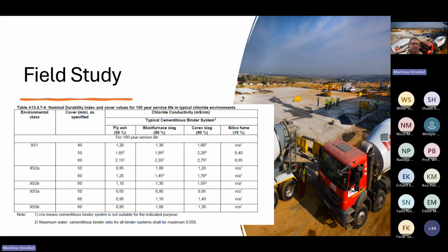In terms of the chloride limits, you can see limits here ranging from a low exposure with cover from 1.2 going to bad conditions at 2.15. Slag values are slightly different, but the 0.25s and the 0.4s are still way under the limits that have been specified. Proving the point again, it's an excellent concrete, nothing wrong with the quality of the concrete. Your expectation as a customer was not met initially because you could not strip your formwork. It's costing money. It's not what was planned on. And yet the concrete is of good quality. So I think it's something to bear in mind that it's not always a bad quality concrete if it does not meet your early strength expectations.